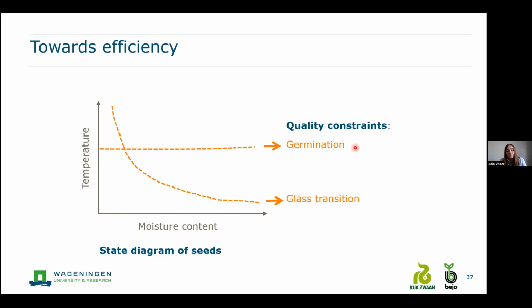How well and how fast do the seeds germinate? And on the other hand, we have this glass transition curve that is perhaps not very clear at the first moment. It actually indicates the optimal storage conditions. So the endpoint, where do we want to reach after the drying? Because if we have a glassy state of the seed, so the cytoplasm of the seed gets in a glassy state, all the oxidative processes or biochemical reactions that can happen and deteriorate the seeds will be slowed down and kind of stopped. So we have a longer storage possibility. So that would be desired.